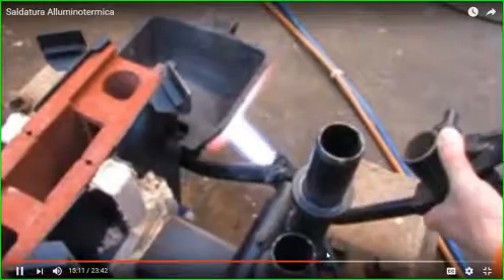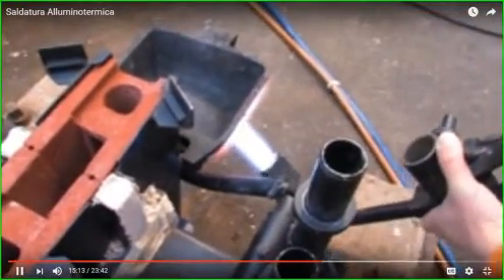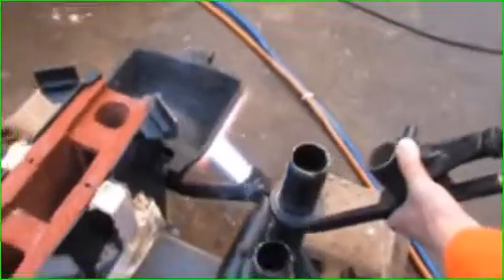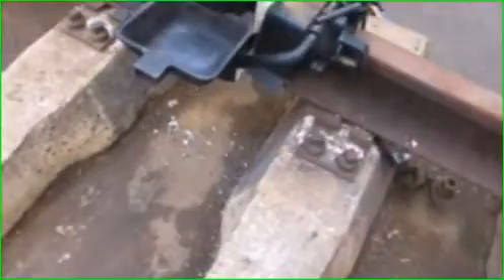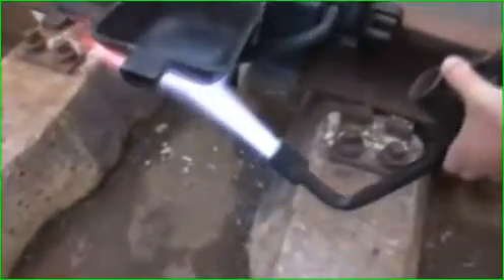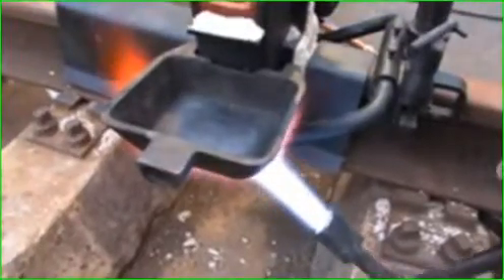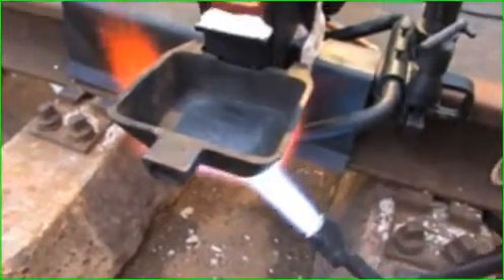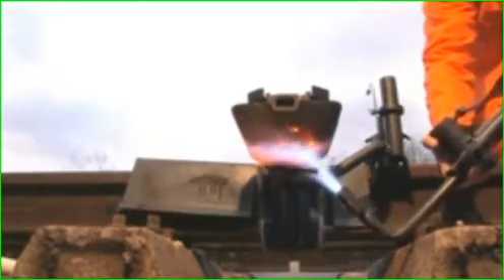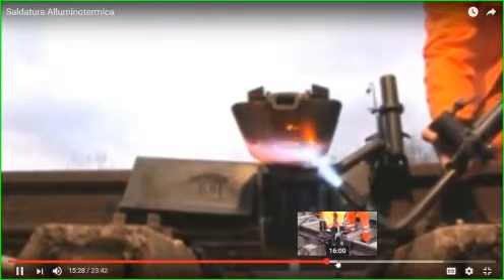First close the combustion valve and then the oxygen valve. Whilst an improper flashback of the flame into the torch happens, the oxygen valve as well as the combustion valve shall quickly be closed. Moist slag pans are to be dried to avoid a dangerous creation of detonating oxyhydrogen gas during the later slag running in.